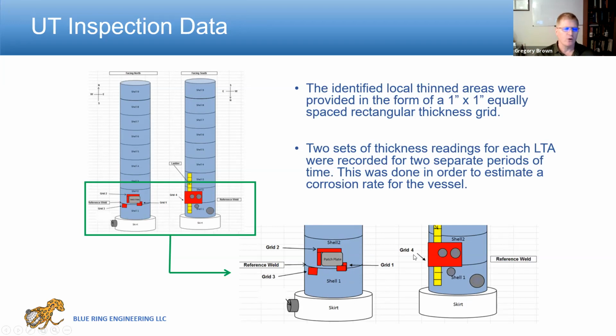Thickness measurements were taken for all the grids. We used those to do the fitness for service assessment. Again, fitness for service is not a replacement for inspection, but works together with inspection, although it can help you determine what type of inspection you need to do, how much resolution you need, and when you need to inspect again. Finally, what you see is grid 4, which was around these nozzles in the second shell course. The grid was a 1-inch inspection grid on all locations.